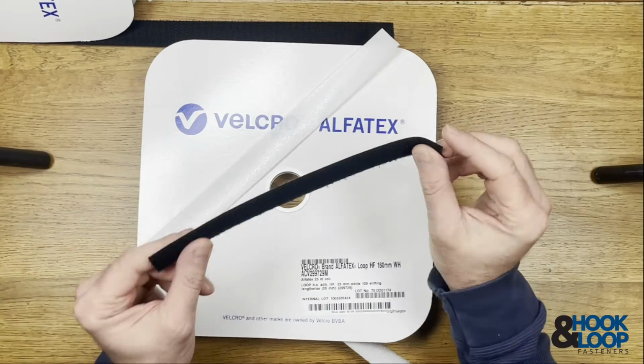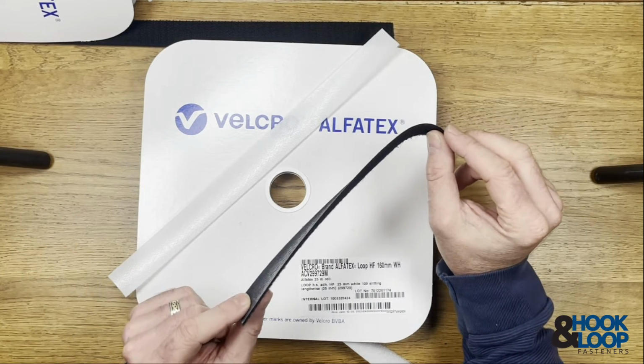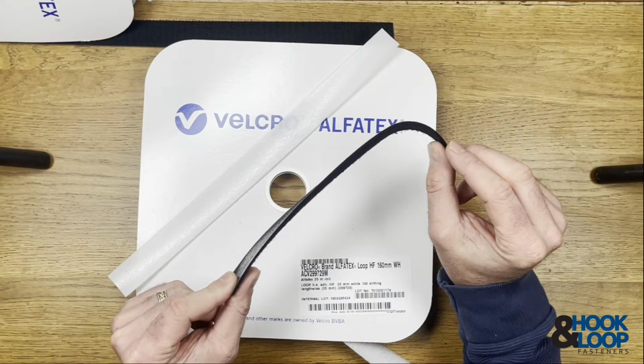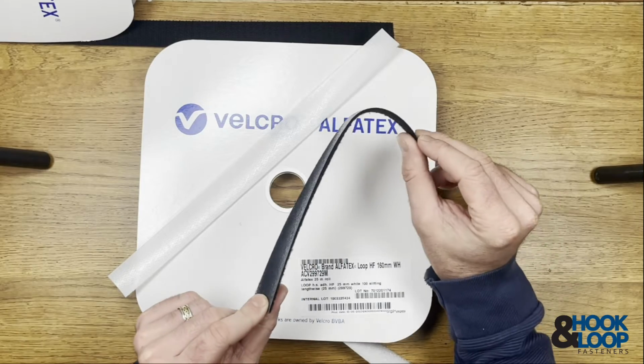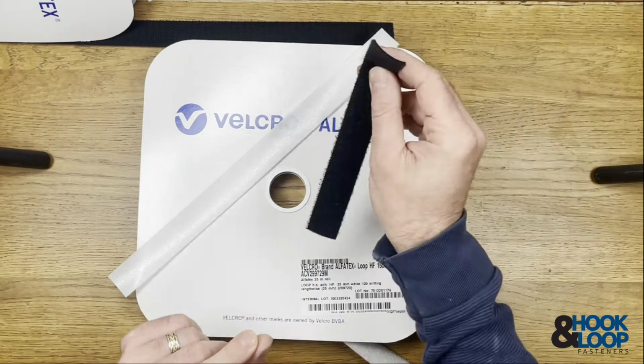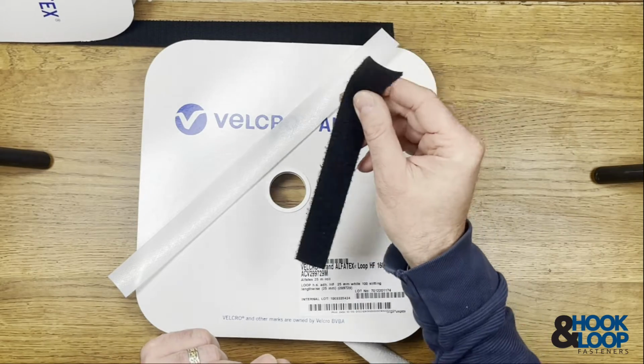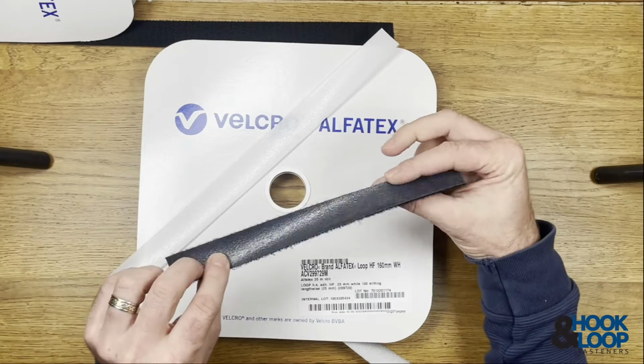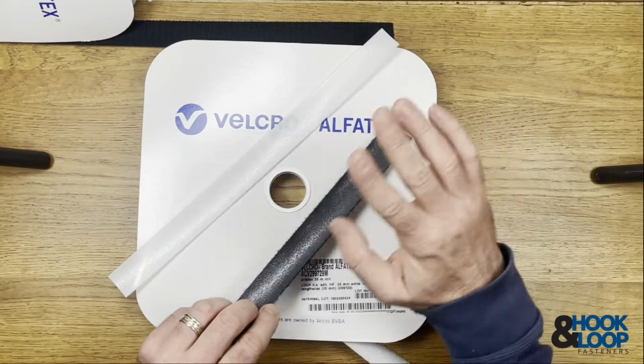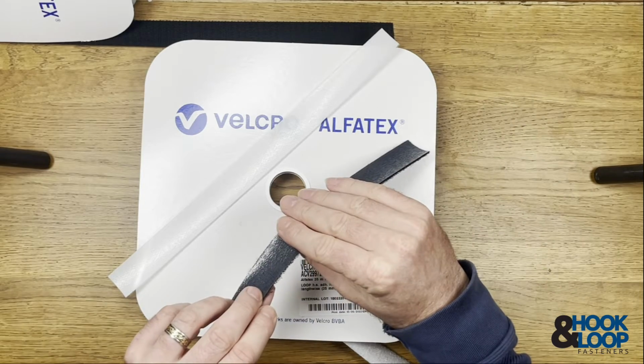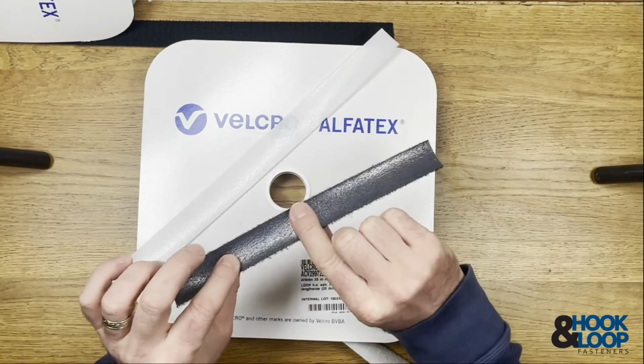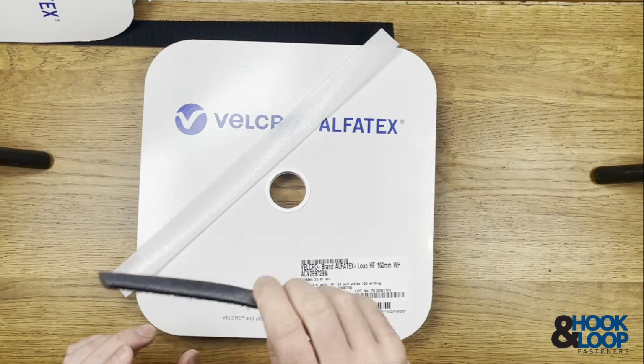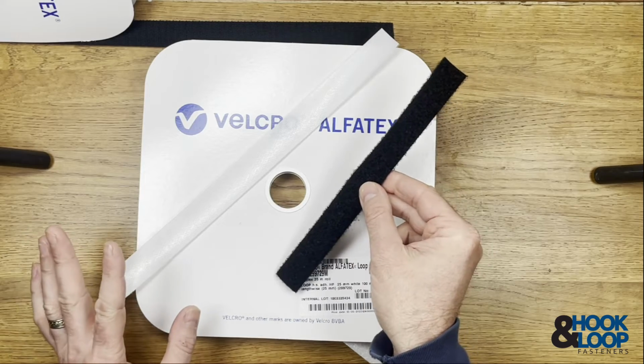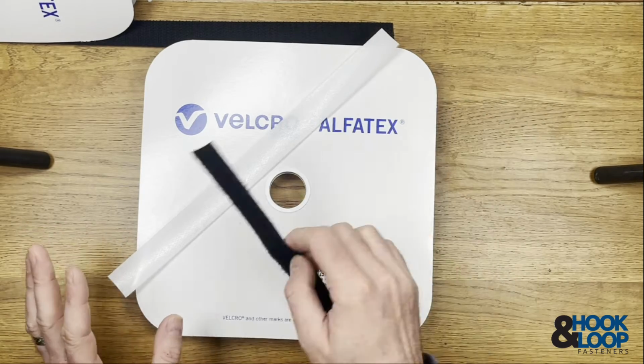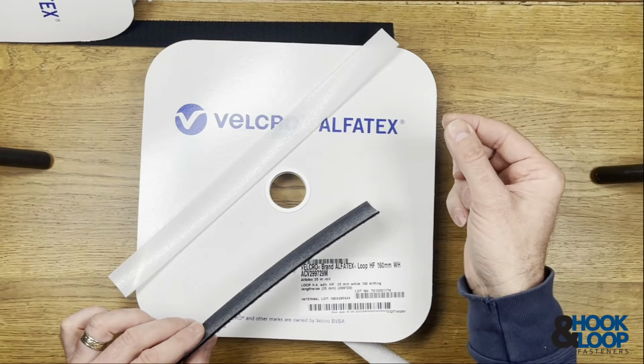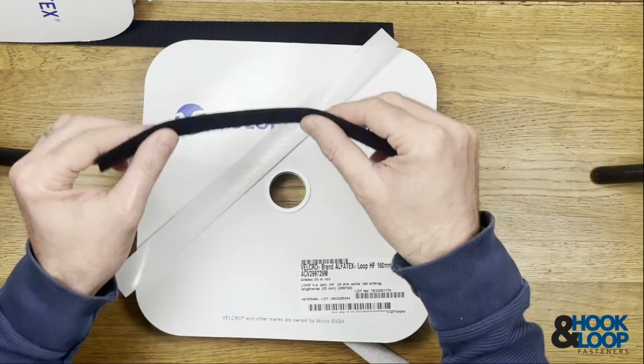So for example, this works particularly well on glass, but you wouldn't want to use ultrasonics or heat. So you would opt for acetone to activate the adhesive and stick it to the glass. It's very, very good for glass. It's also good on plastics, and again, depending on the plastic, you could opt to use acetone on the adhesive and apply to the plastic. It's not suitable for aluminium or metals. For that, you just want a conventional peel the release paper and stick a PSA adhesive.